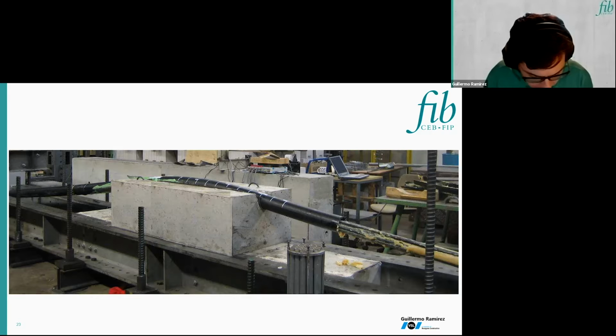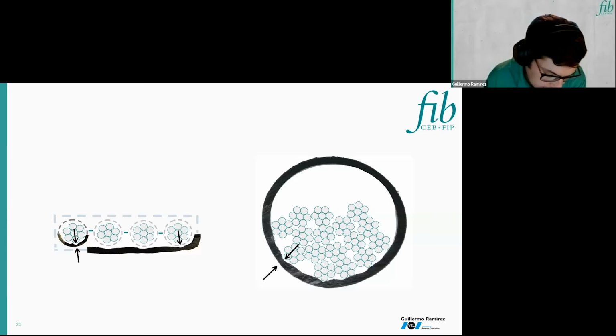The European assessment document, which has a very long name, 1600004000301, which replaced the ETAG 013, for example, defines testing procedures for deviations with constant radius, as we can see in the picture, and deviations around sharp edges, as we saw in the previous slide. The acceptance criteria for all these tests is focused on the minimum thickness of the PE sheathing after the test.